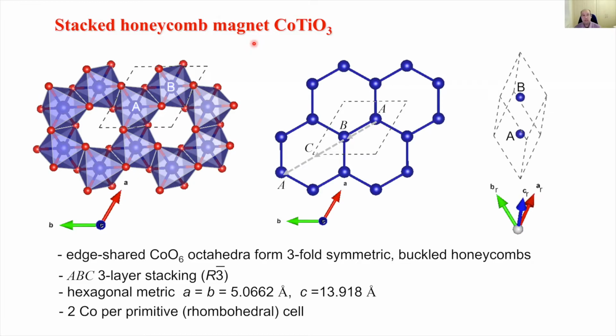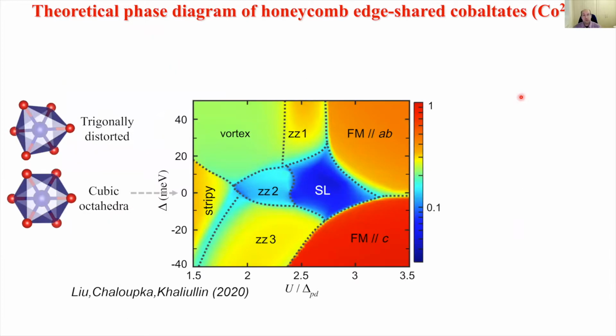An important point of this is that the 3-dimensional stacking doesn't introduce a new number of sublattices, but can still be described in terms of a primitive cell of 2 sublattices. So for a single layer, we have sublattices A and B, but even if we go to the 3D stacking, this can still be described formally through a rhombohedral crystal structure, but fundamentally just with 2 sublattices A and B. So understanding the physics of edge-shared honeycomb arrangements is actually quite interesting from other points of view as well.